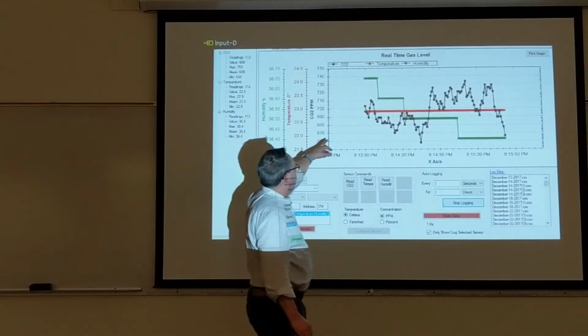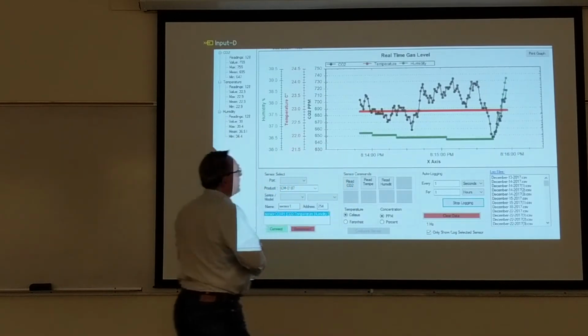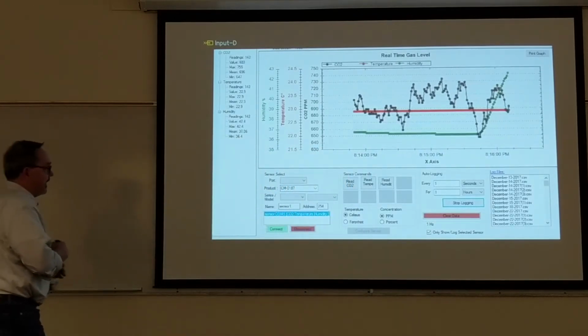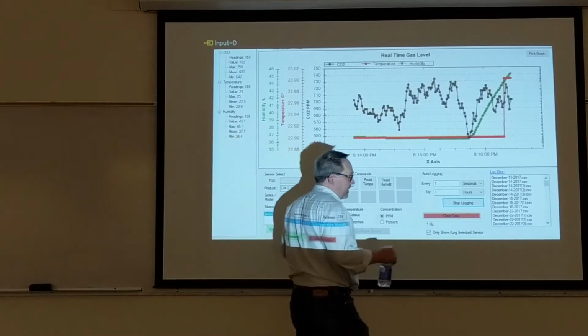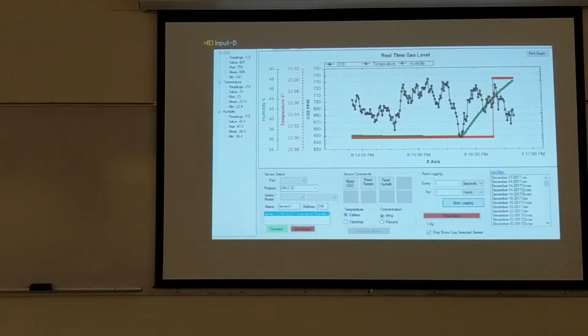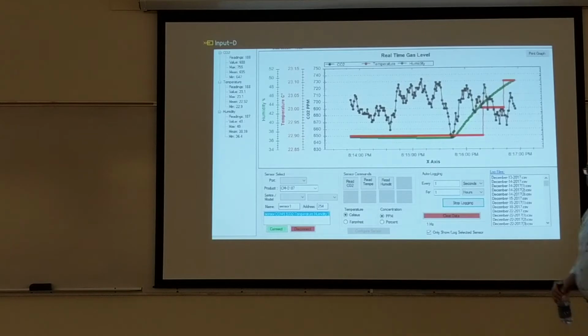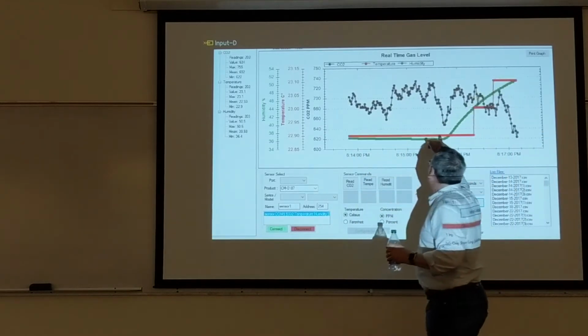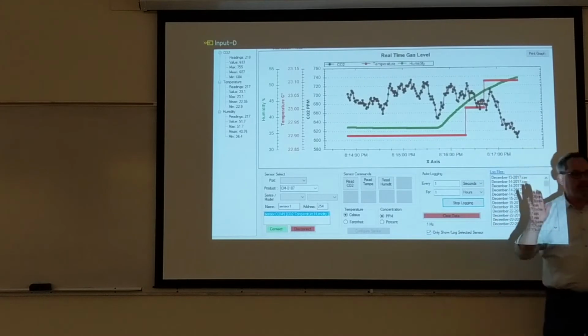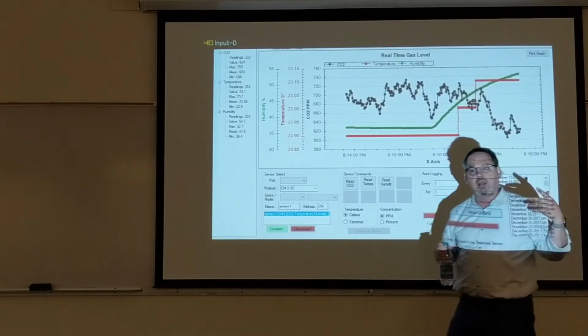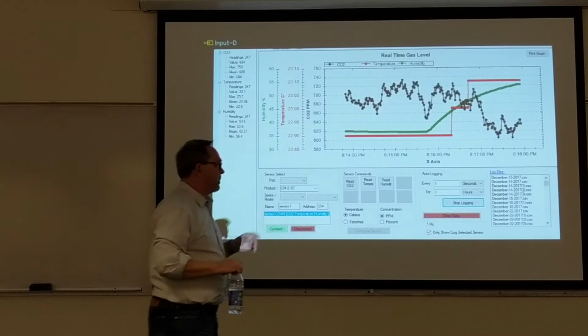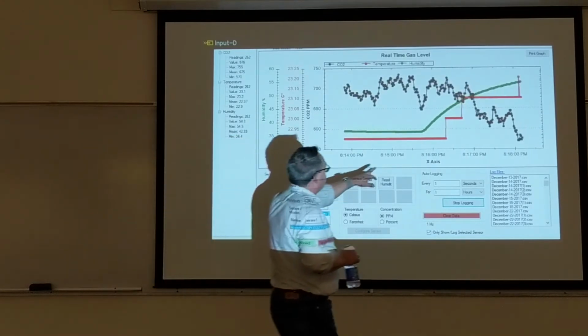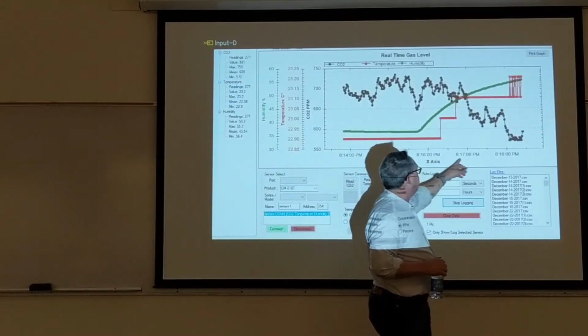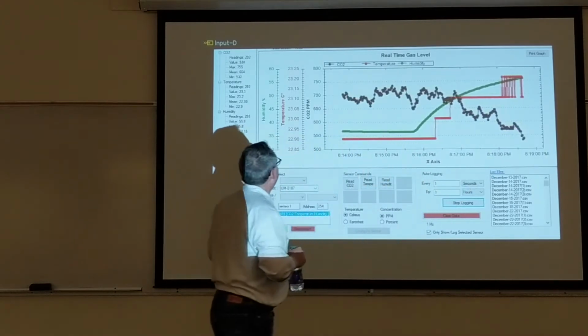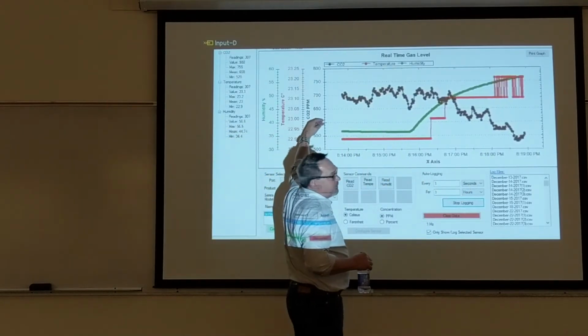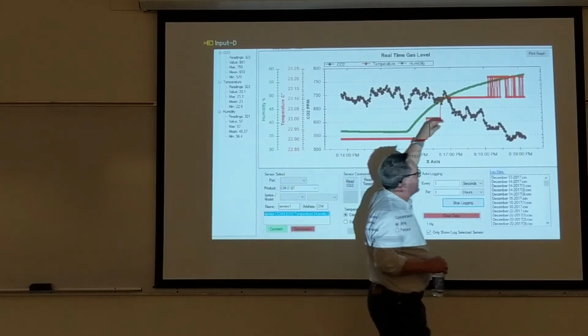With the monitor, we track the CO2 content in black, the temperature in red, and the relative humidity in green. The important thing is we isolate a bit of room air against the tailings and see what happens to that isolated bit of room air over time. We can tell when we've isolated it because the relative humidity starts to spike up, because these tailings are partially water saturated, about 30% water saturated. You can see from this graph here, we isolated at about 816. So here's 2 minutes in, and we've pulled about 100 ppm of CO2 from the air above those tailings.